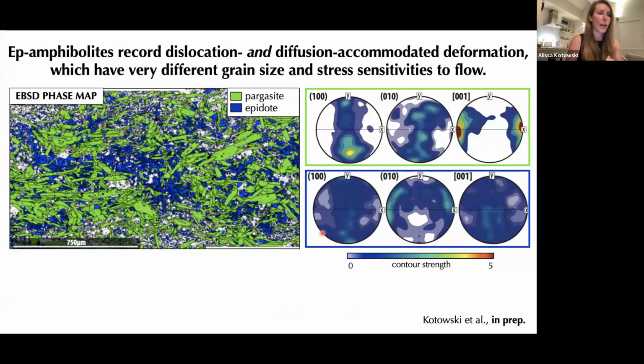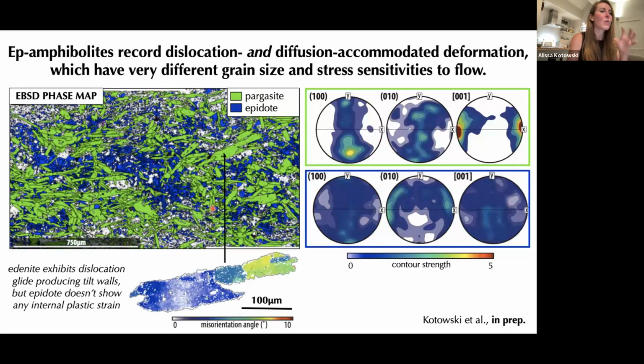So these microstructures are very complicated, but also really fascinating. In this phase map here, we have coarse-grained pargasite in green with a moderate strength crystallographic preferred orientation. And we have epidote, very fine-grained in this blue color with little to no crystallographic preferred orientation. If we think about intracrystalline plastic strain, then we see dislocation accommodated deformation in amphibole crystals. So this manifests as this systematic undulose extinction sweeping through and these tilt walls, these dislocation walls that are forming as these dislocations are gliding through this crystal. So we don't see anything like this if you make the same kinds of maps for epidote.